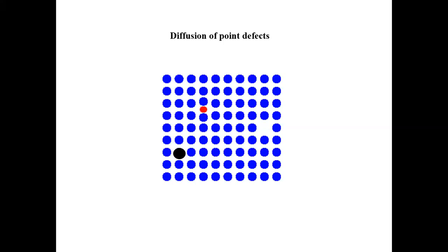So this means that vacancy and atom self-diffusion are the same processes, but if you look at a vacancy, it apparently moves much faster, right? Because it moves all the time. But if you come to the particle, it's not, right? It only moved once and it's going to stay there and wait for another vacancy to come nearby and it can move again, right?